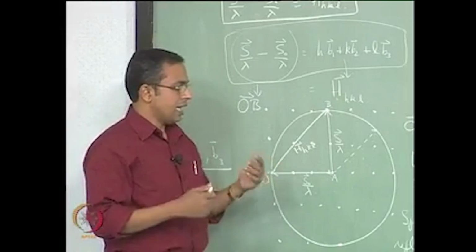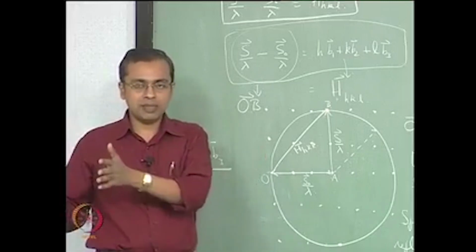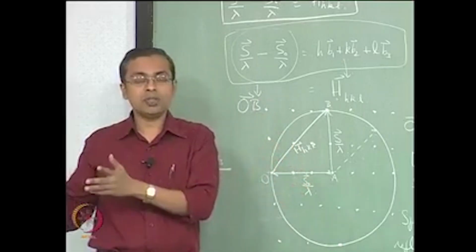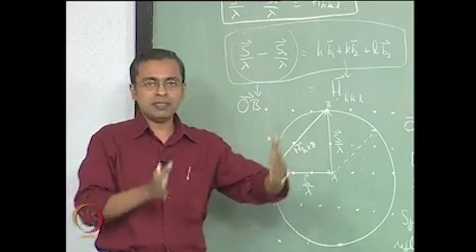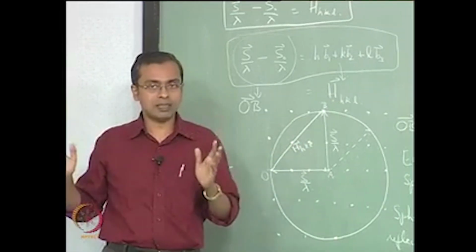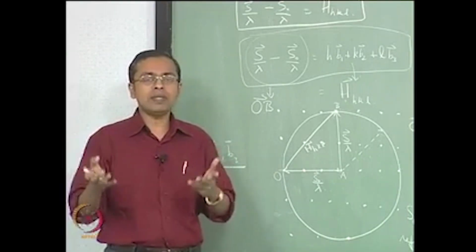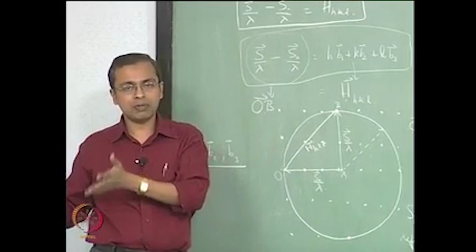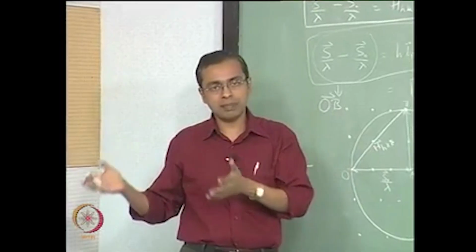So that is one piece of information, and we have also seen in this class that when you do this transformation from real space to reciprocal space, some structure that has a certain geometrical layout in real space may have a different geometrical layout in reciprocal space. In the case of simple cubic, it happens to have the same layout. In the case of FCC and BCC, it has a different layout in reciprocal space. The information is still the original material's information, it is only the representation in reciprocal space that has a certain style, certain layout, and it so happens by chance that when you take a face centered cubic material, its representation in reciprocal space happens to be that of a body centered cube, and if you take a body centered cubic material, its representation in reciprocal space happens to be a face centered cube.